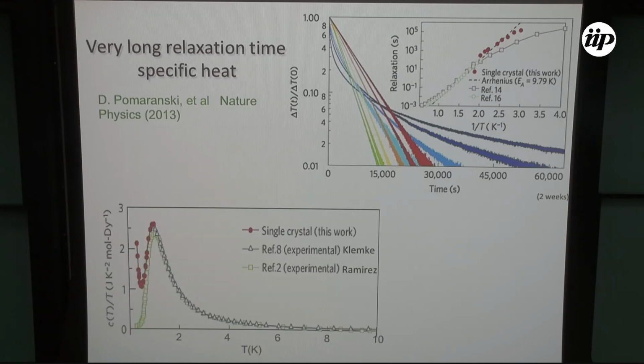So now when they compared their results with results by other people, for example, the one shown here is Ramirez, this one here is Klemke, and this is the measurements we did. And this is the measurements I showed you at the beginning, that the intermediate range of temperatures works well with the monopolar picture. But when they waited for long enough, they saw that there was this upturn that seemed to indicate that if you waited long enough, you could see order. Okay, so if that was what's happening here, then if I do the same experiment with neutrons, I should be able to see the order that is developing there. And the only thing you need to do is to wait.